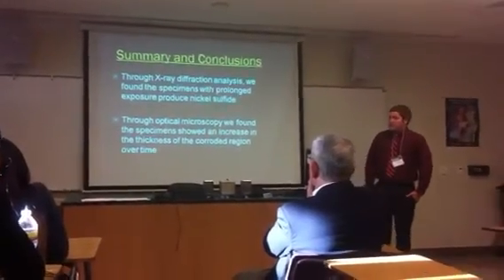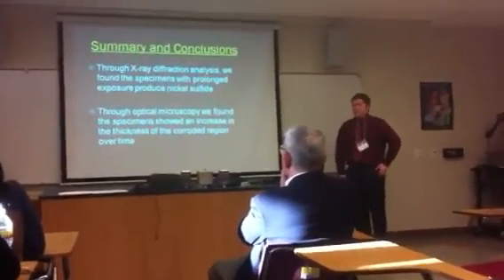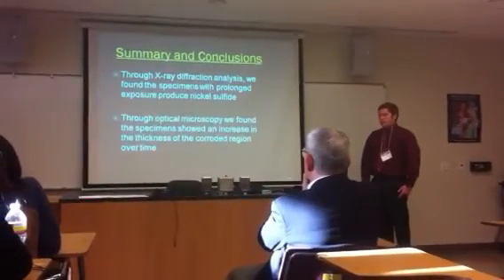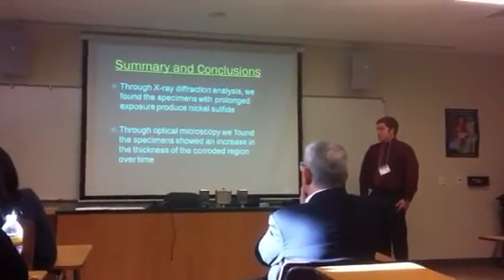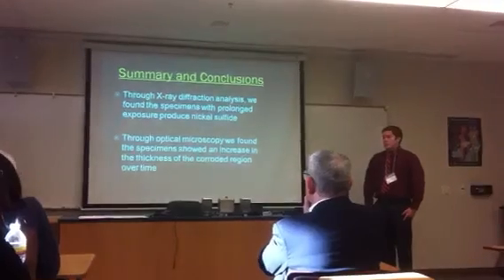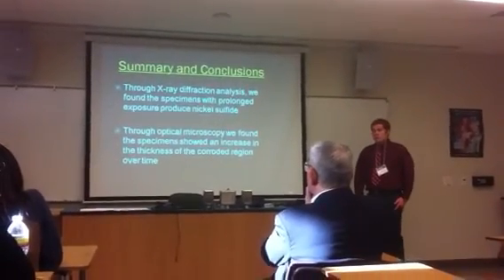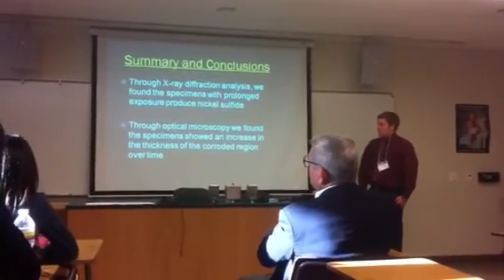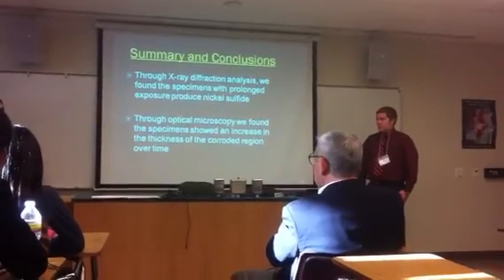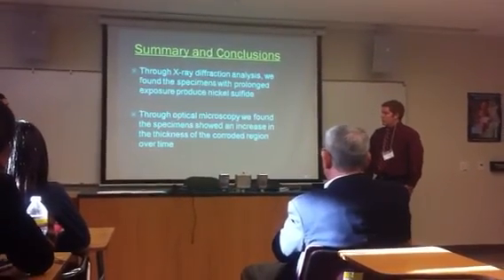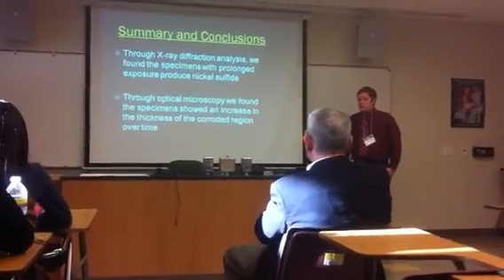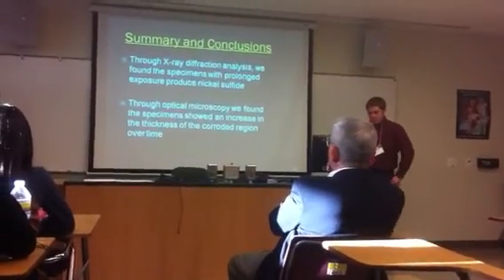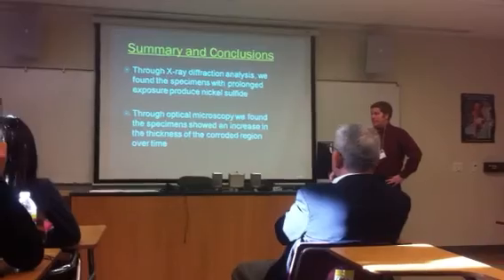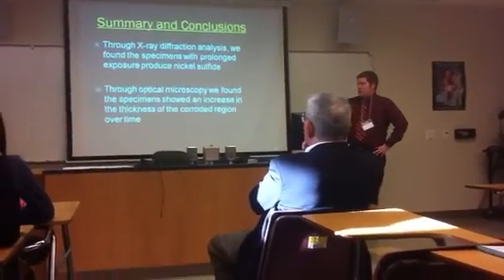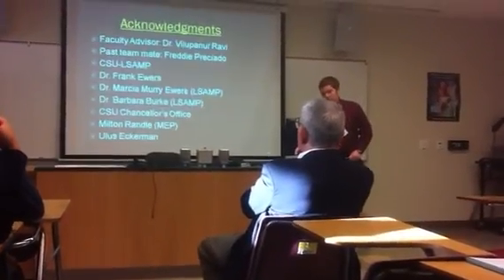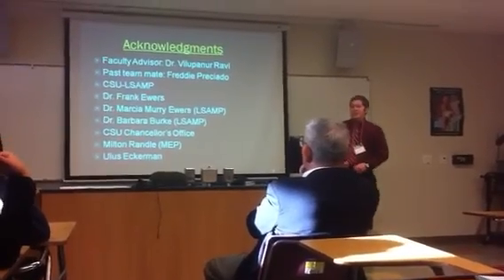As Brian mentioned, we also performed X-ray diffraction, from which we have found that as the nickel 200 is exposed to Na2SO4 at 900 degrees Celsius, nickel sulfide is being produced. However, we're still in the process of determining whether, as time increases, more nickel sulfide is produced in the sample. And through optical microscopy, as Agustin mentioned, as time increases, the thickness of the corrosion layer is increased. And so we'd like to thank